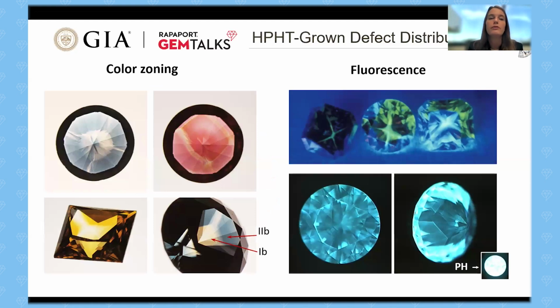And this can be observed in fancy colored diamonds through color zonation. So again, these impurities, these defects are what's causing the color. Higher concentrations go into certain growth sectors, and we can see that through color zonation, but even through fluorescence techniques where we illuminate the sample with UV light. In fancy colored HPHT grown diamonds, you might be able to see that distribution even using a standard gem lamp with a shortwave UV. Or alternatively, you can use deep UV from an instrument such as the DiamondView, where the wavelength is less than 225 nanometers,